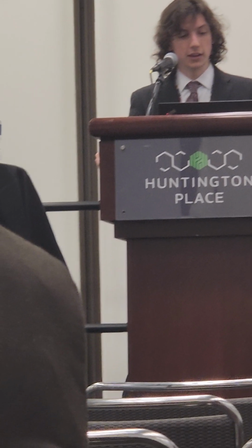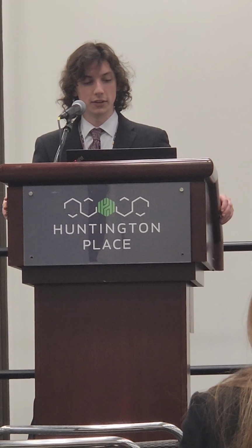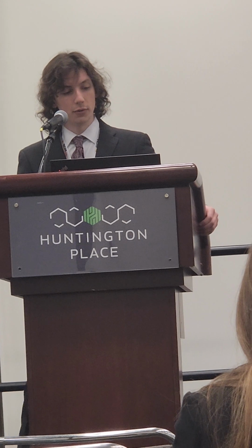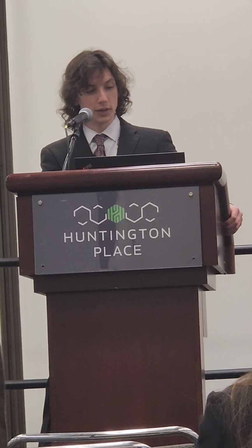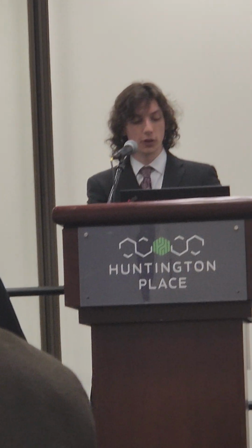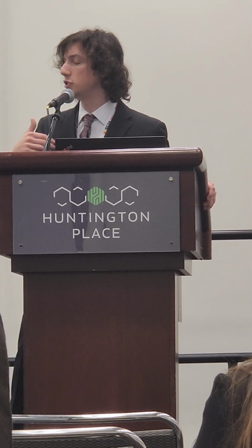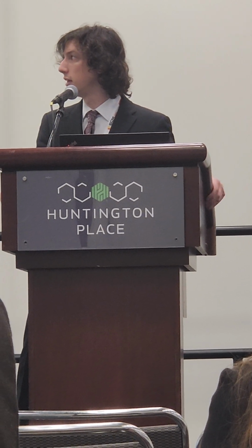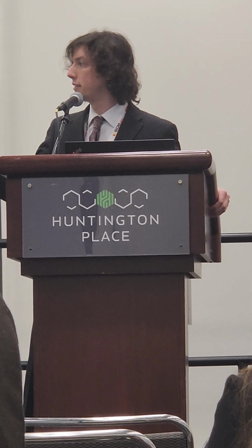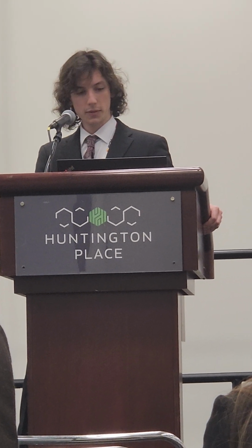And for the modified alloy, similarly reflective after 0 minutes, you have that shelf along the right side, and abnormal grain growth after 328 minutes does not see as much of a sloping down with an increased amount of work. It's just generally a higher amount of abnormal grain growth across most conditions, and between any conditions of the standard alloy or the modified alloy, the 328 hold time of the modified alloy had the most abnormal grain growth in general.